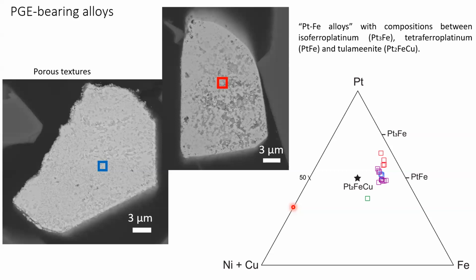Just to be difficult, what if it was a sulfide melt and it's concentrated, the PGMs crystallized from that, and now you've lost a lot of sulfur because it's all serpentinized? Yes, that is an option. You could have these sulfur and arsenic melts, and you form this primary PGM, and then you have this secondary process that promotes some desulfurization, and you could get these alloys too.